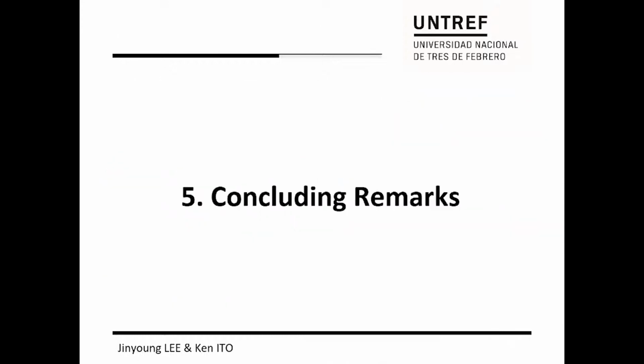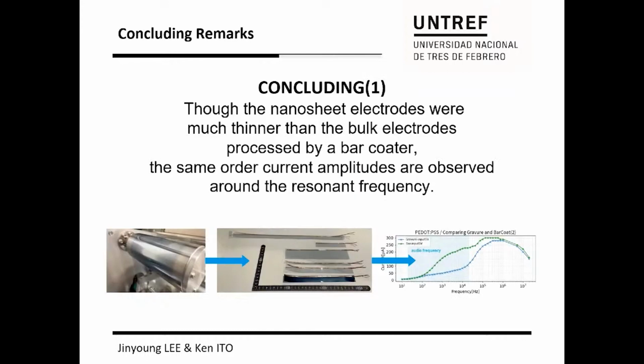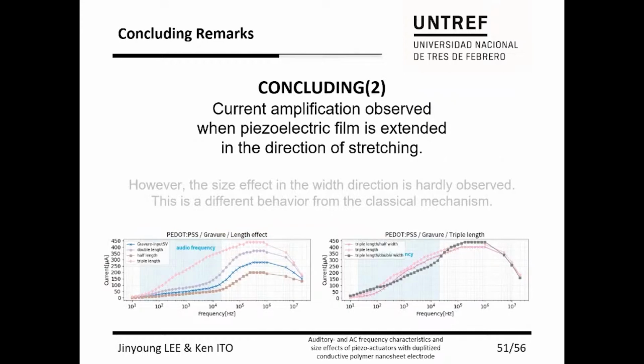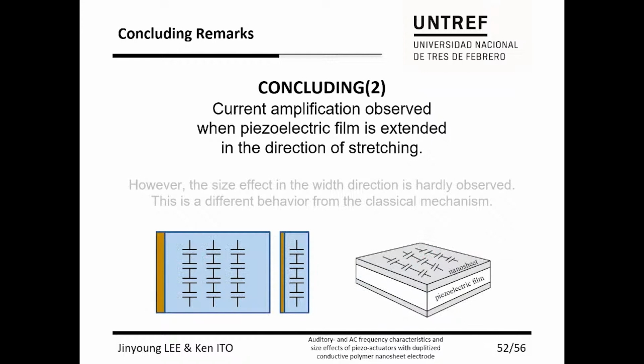Let me summarize this study. Using a bar coater, we fabricated a piezo-ribbon actuator, and we expect to reach the level of practical output for actuators by enhancing conductivity. We also observed current amplification when the piezoelectric film is extended in the direction of stretching. On the other hand, the size effect with changing the width is hardly observed. This is a different behavior from the classical mechanism. We are considering the quantum effects of conductive polymers, and the research is in progress.